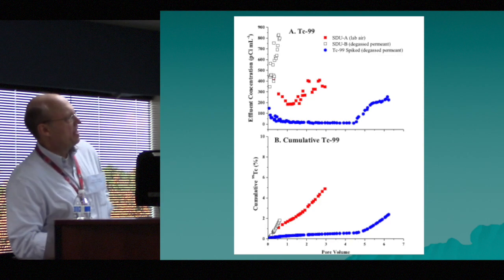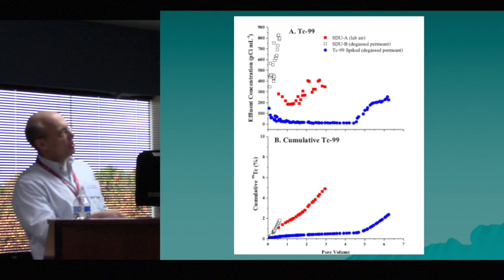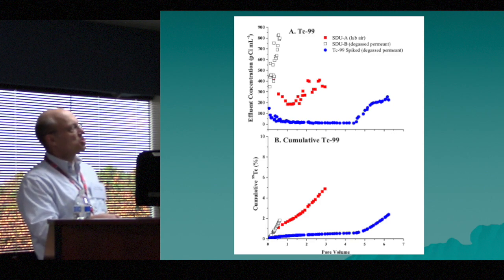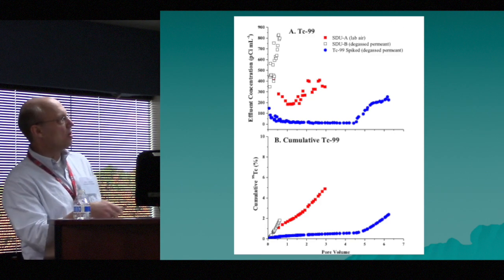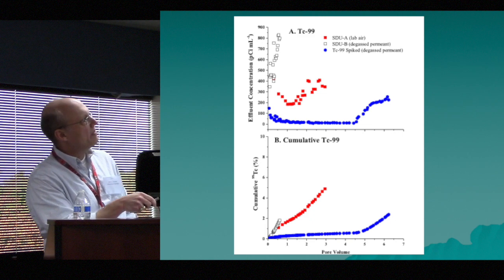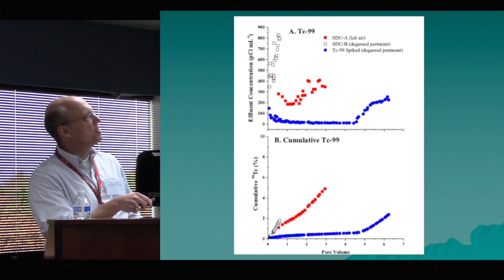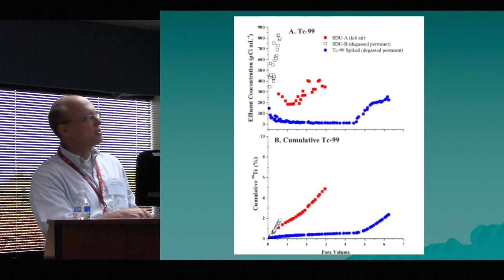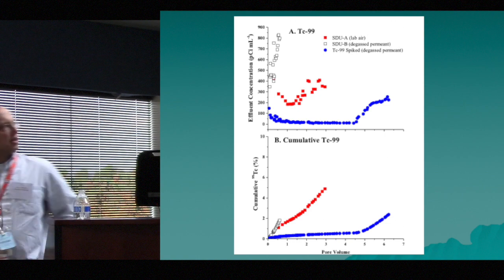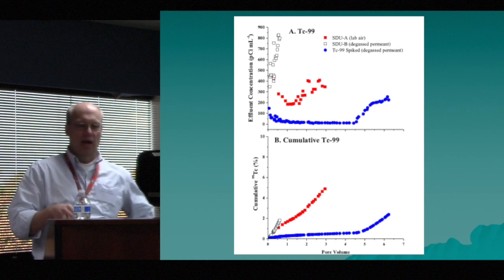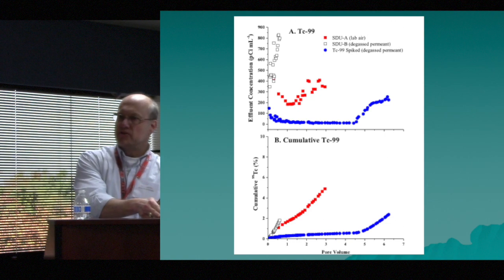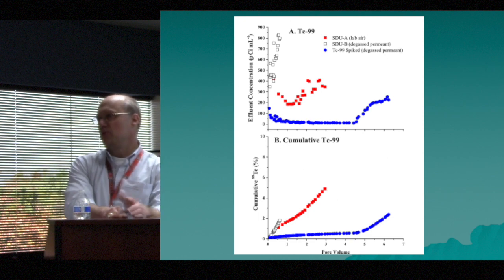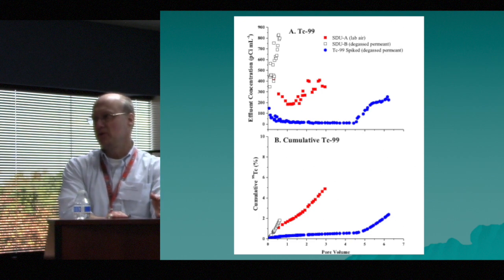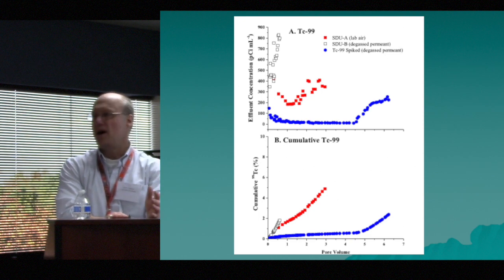If we look at the technetium, one thing that's important to note is that the levels are much lower than what the inlet levels were with the solutions. But we have the SDU-A and this SDU-B samples. We still have fairly high technetium levels coming out in these initial pore volumes. And what you can say, though, is that at those initial high pHs, these are fairly consistent with what the technetium oxide solubilities would be, even though they're a bit high.